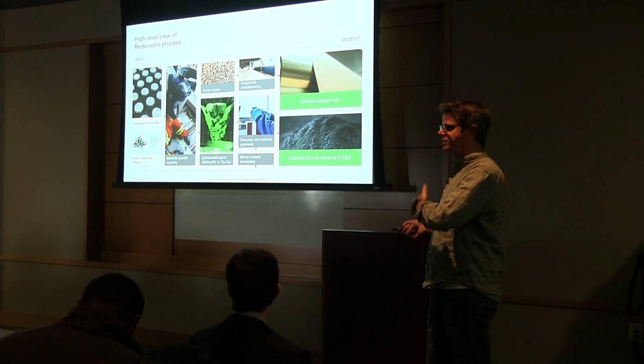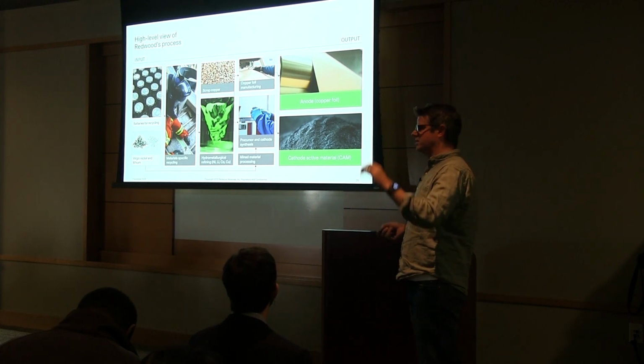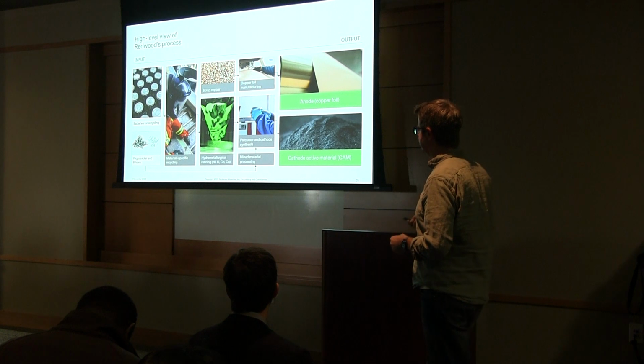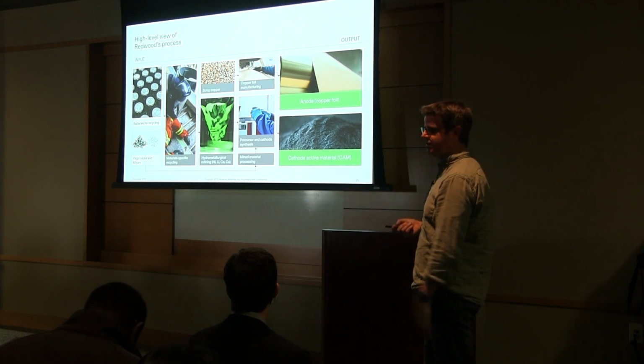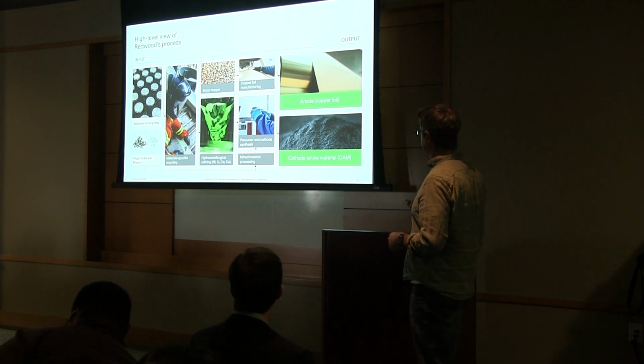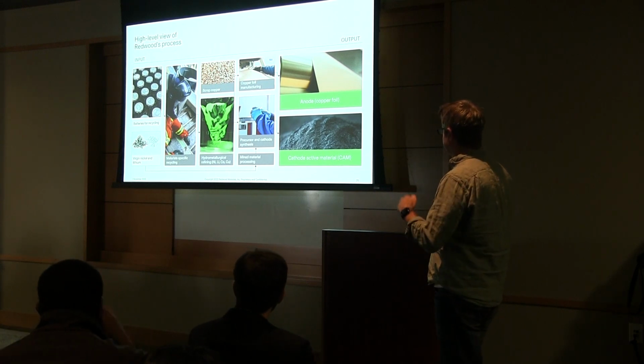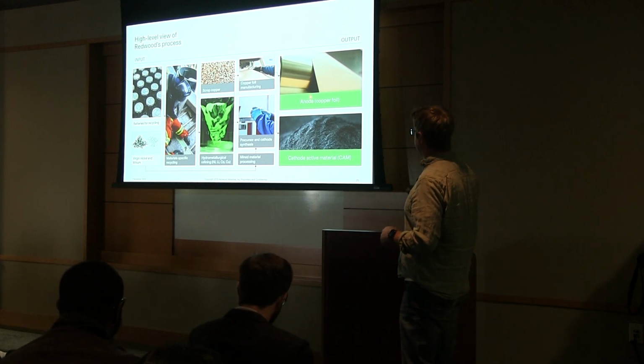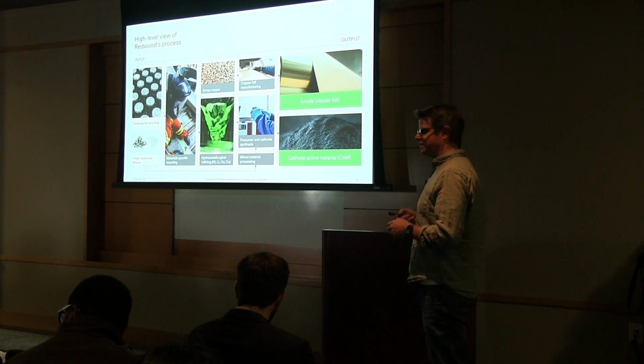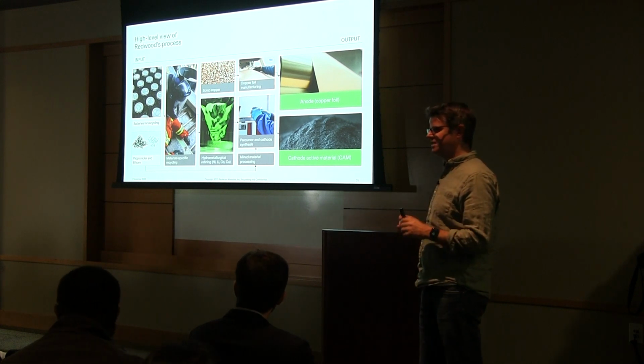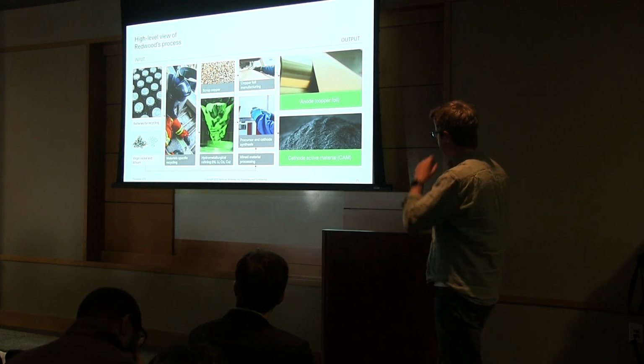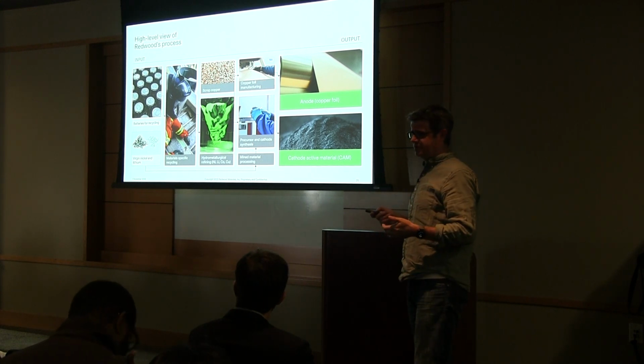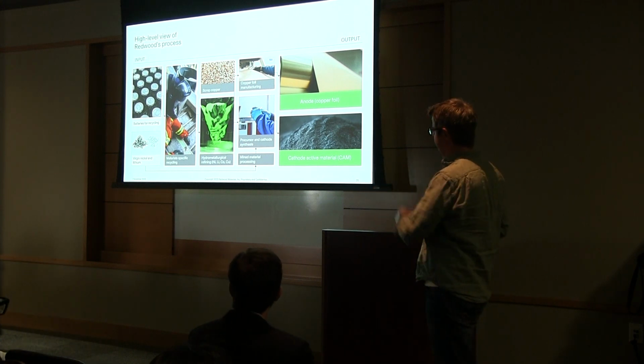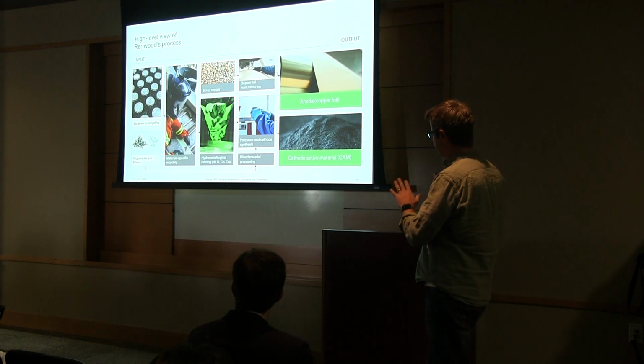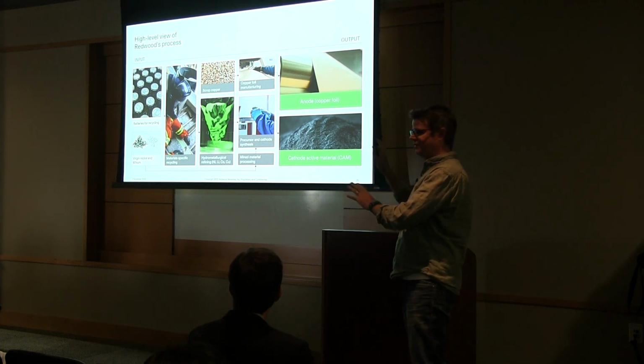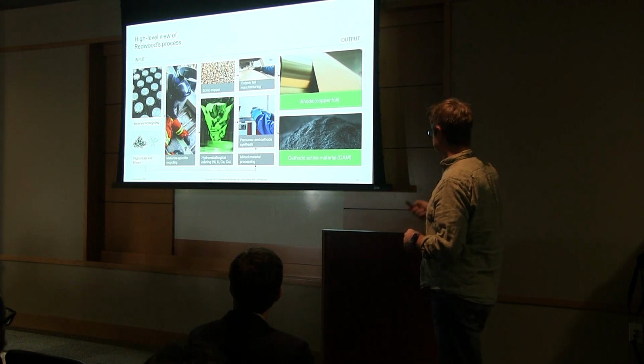And the mined nickel materials will still be with us as we scale battery production, simply because we don't have the recycled units. Where we want to get to is recycling supplying most of the metals, but at the moment that's not possible. So we go through precursor, mix it with lithium, and we produce our CAM. On the copper foil, again, this can take recycled copper units. That is quite difficult to do because the copper needs to be extremely pure. But essentially, anode manufacturing is an electrodeposition process done on continuous titanium drums, and I've got a few photos of that later. But that's how the recycling processes fit into achieving these two final products.